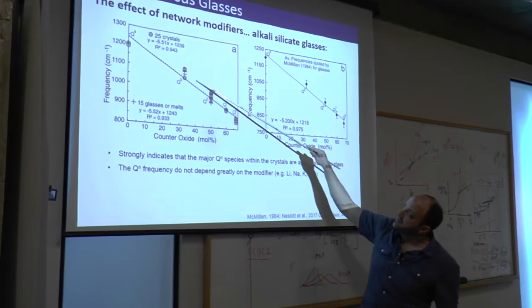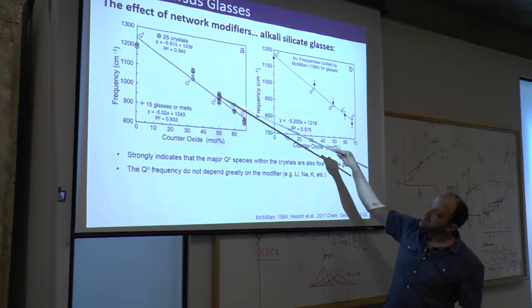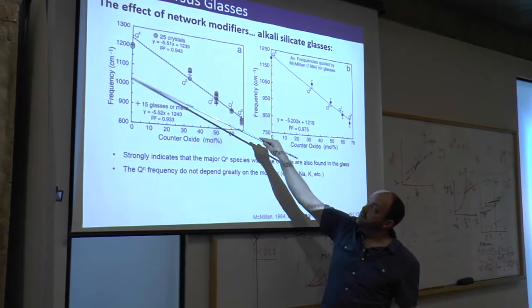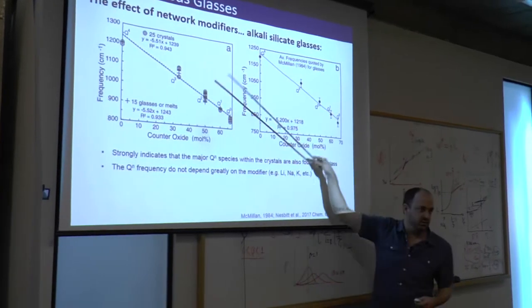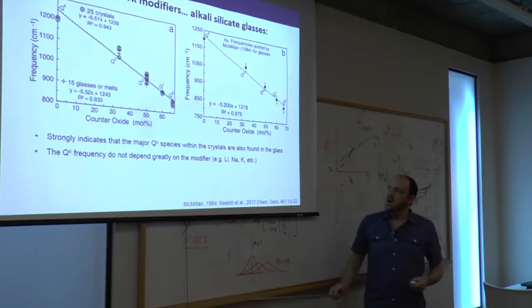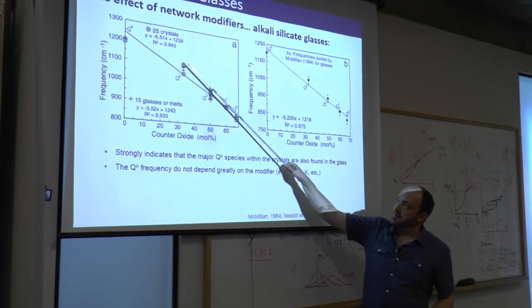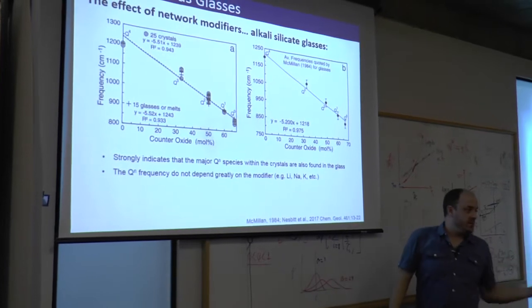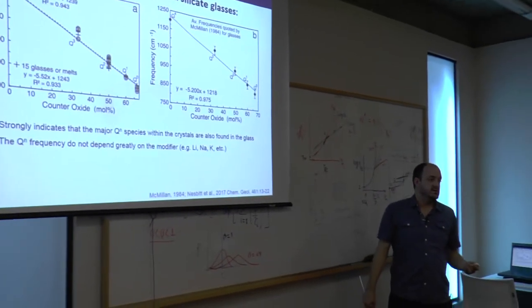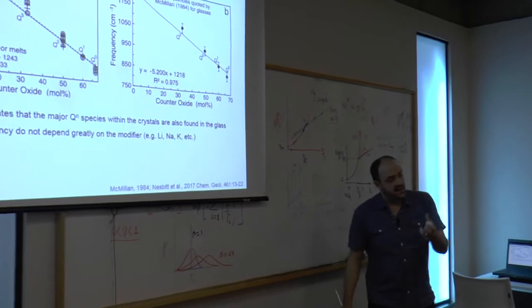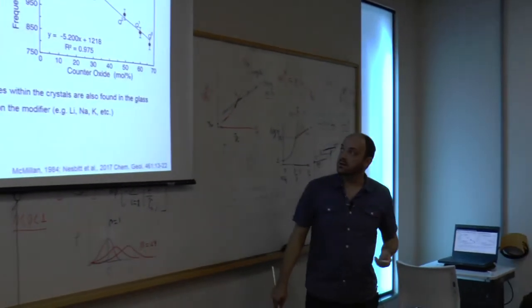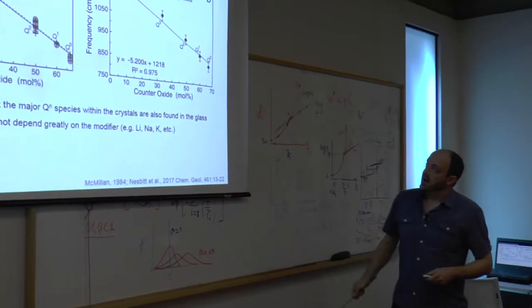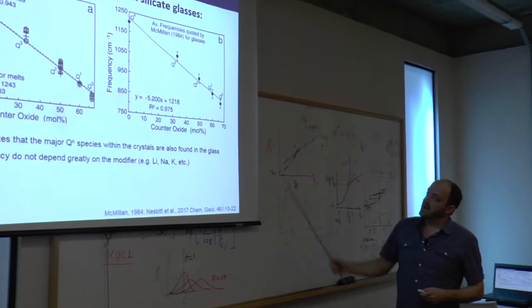In this case, for Q2 or Q3, there appears to be the most. It's about 50 wave numbers or so. So there's a little bit of play in here. There's a little bit of changes. But these results are pretty good. So the main dominant structural unit, the main QN species that's found in the crystal, is the same main dominant species found in the glass. And they've redone this for more glasses.